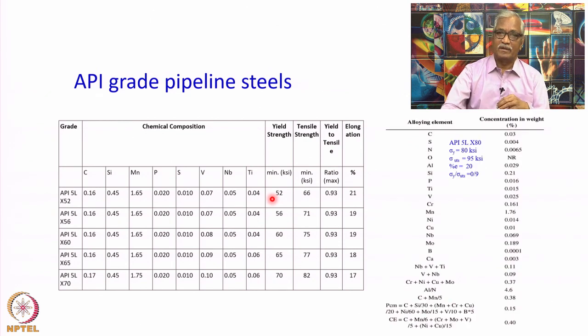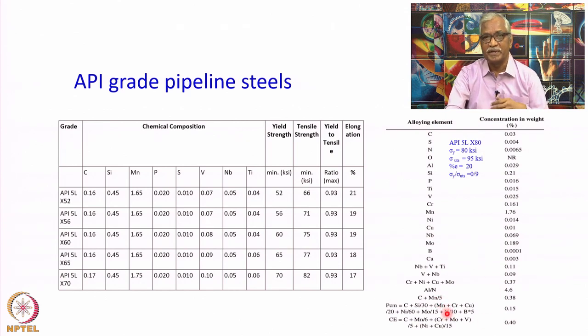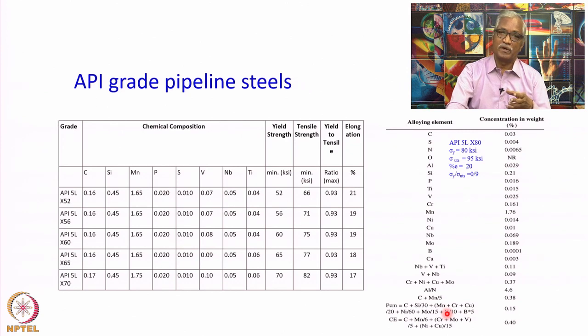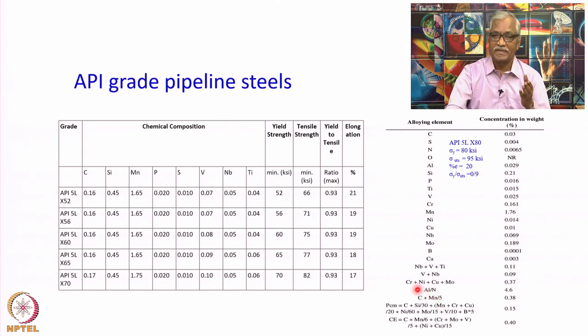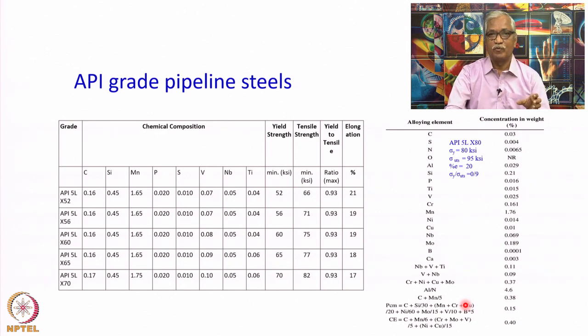Subsequently, there has been another steel, API 5L X80, where the strength level has gone to 80 KSI and the UTS value to 95 KSI. Here too, micro-alloying elements are added to refine grain structures and bring in phases providing higher strength and ductility. If you look at the composition, there is hardly any significant increase in elements like chromium which offers passivation. As a consequence, the corrosion behavior of all these steels is very much identical, and when talking about corrosion of oil and gas pipelines, we do not distinguish significantly between these steels.